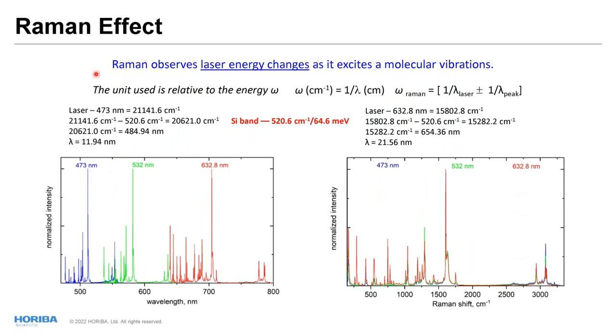Besides this, we have a little bit different complication due to the band gap of the material. In Raman scattering, if we see from this diagram, we're going to the virtual state. In classical Raman scattering, we're going something between the gap. However, if we have a laser which is very close to the gap, we may have pre-resonance Raman scattering. And if the energy of laser excitation is larger than the gap of the material, we have resonance Raman scattering. This becomes an important issue when you study some materials.